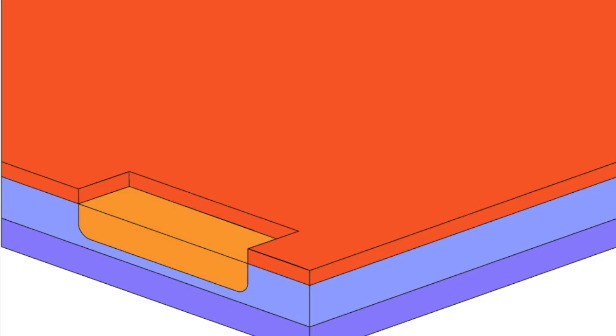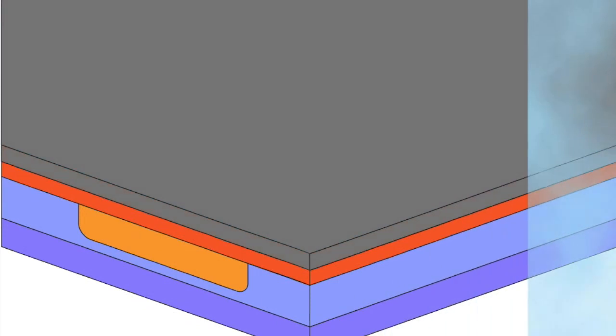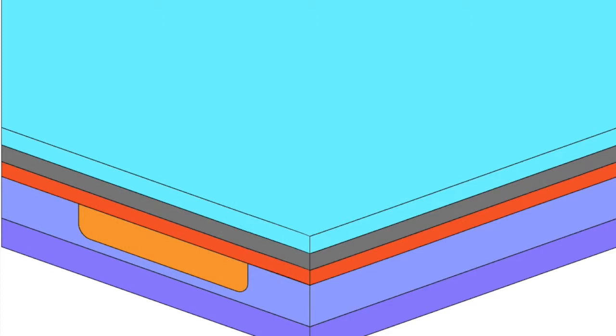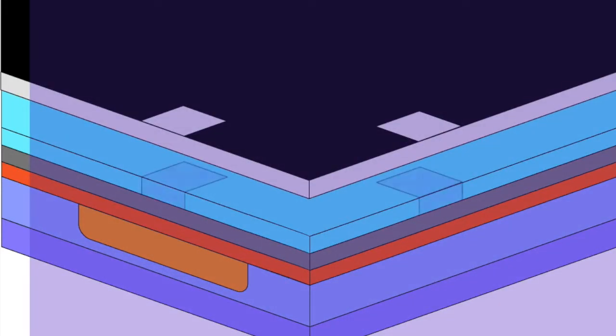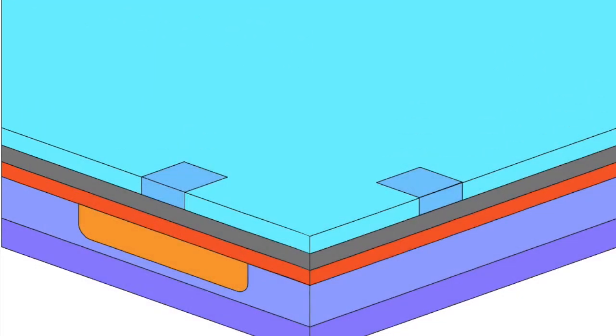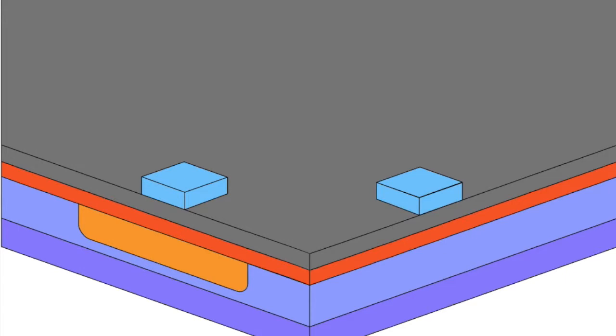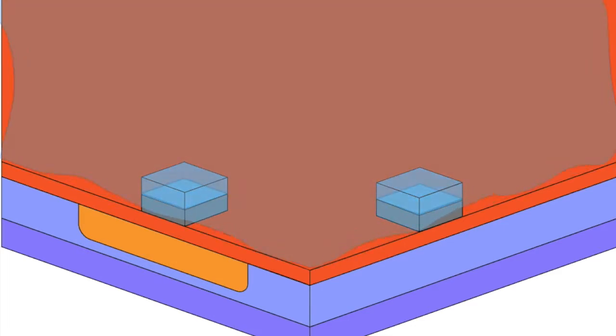Another thin layer of silicon dioxide called the gate oxide is grown over the N-well regions. The oxide is actually grown over the entire wafer but grows much faster over the wells. Using a CVD process, a layer of polysilicon is deposited over the gate oxide. The polysilicon will form the device gates. Another patterning process is now accomplished beginning with the application of a layer of resist followed by a soft bake. The second mask is used to expose the resist to form the device gates in the polysilicon. The exposed resist is developed, removing the unwanted areas of resist, followed by a hard bake. A dry or wet etch is accomplished removing the unwanted areas of polysilicon down to the gate oxide. The remaining resist is removed and the wafer cleaned.